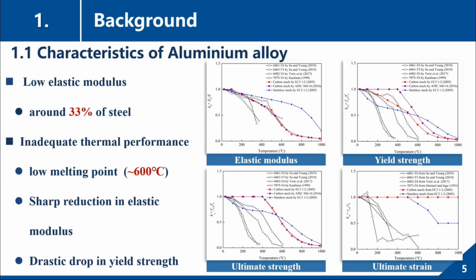More than this, the elevated temperature performance of aluminum alloy structures is also not as good as steel structures. First, it will melt at around 600 centigrade. And it has a sharp reduction in elastic modulus and yield stress when the temperature is higher than 300 centigrade. The pictures on the right-hand side present this characteristic.